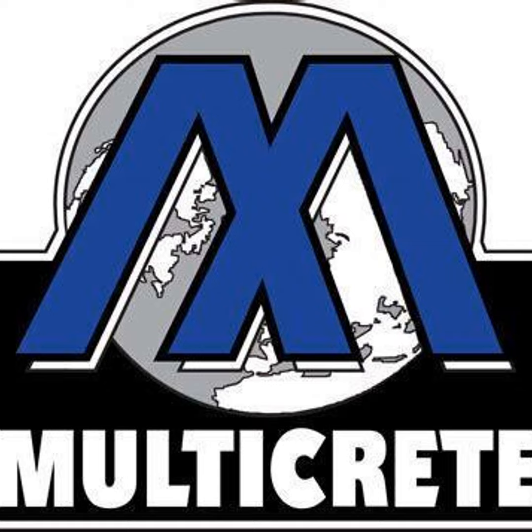Yeah, you want to talk about a way to cut carbon, not having to use burnt up lime, just use regular limestone, and that replaces 10% of your clinker. I mean, boom, you've just got an 8 to 10% carbon emissions reduction. Congratulations. It's that easy. And at equal performance, right. I hope that we'll start selling that at an equal price to standard type 1, 2, and we can get this thing in the market.